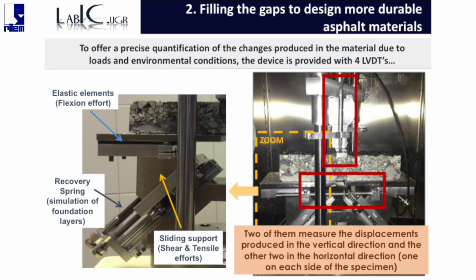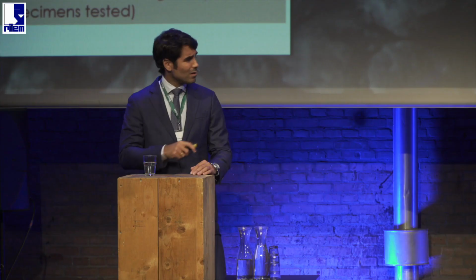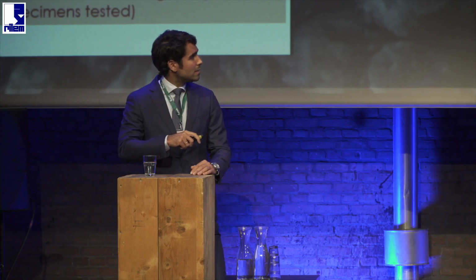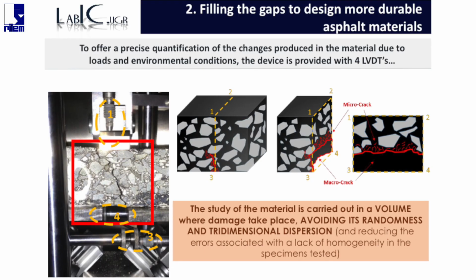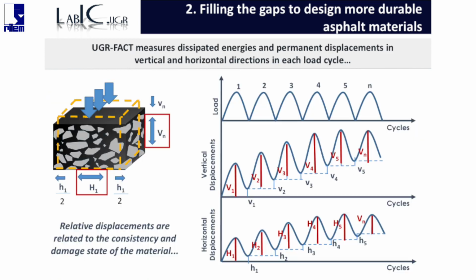So this configuration allows us the evaluation of the material inside a volume, avoiding its randomness and the 3-dimensional dispersion of the damage produced in the material during the test. Taking that information, what we do is record every relative displacement produced in the asphalt material in both directions, in the vertical and in the horizontal one.